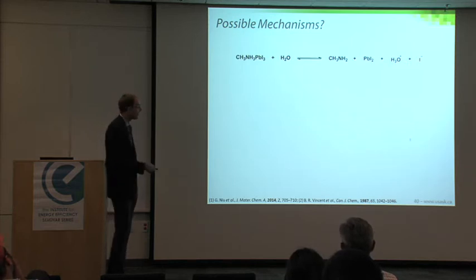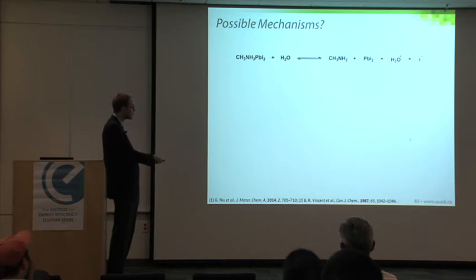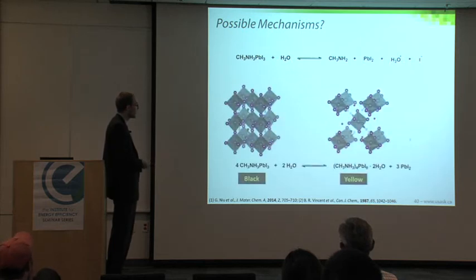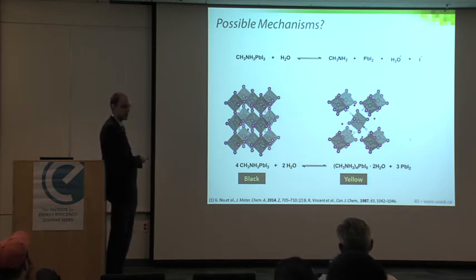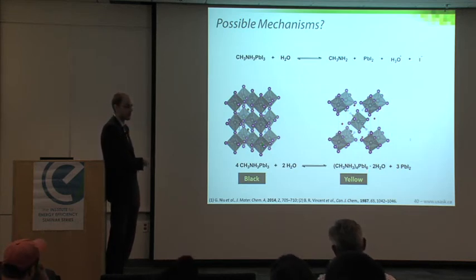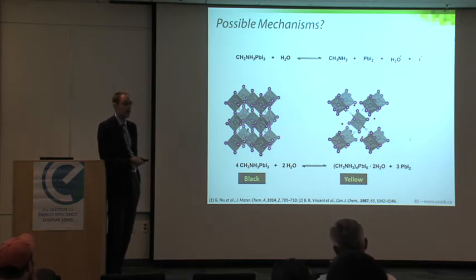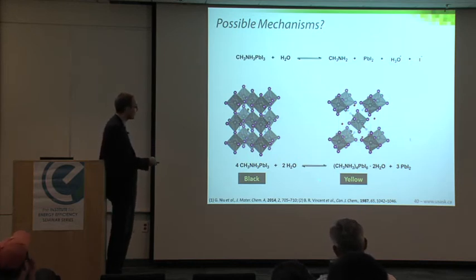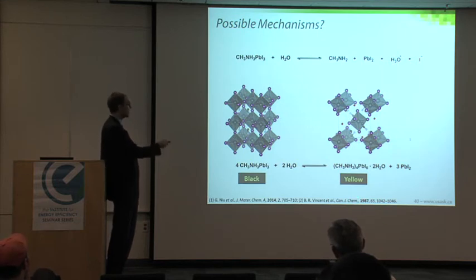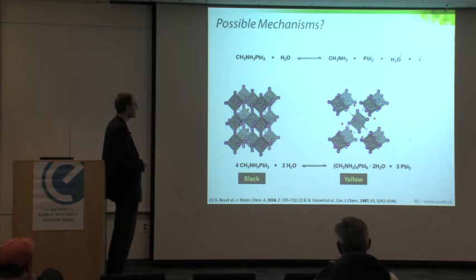This is where this paper comes in from the Canadian Journal of Chemistry out of a group at Dalhousie University from 1987, when I was much younger. They structurally characterized this material on crystallizing the perovskite from an aqueous solution. And it's a methylammonium lead iodide hydrate, which actually corresponds really nicely to our mystery phase in our grazing incidence X-ray diffraction data. So it was a bit of a back to the future experiment where we did the experiment, got the data, saw the phase, and then rediscovered that somebody had done it 30 years previously.